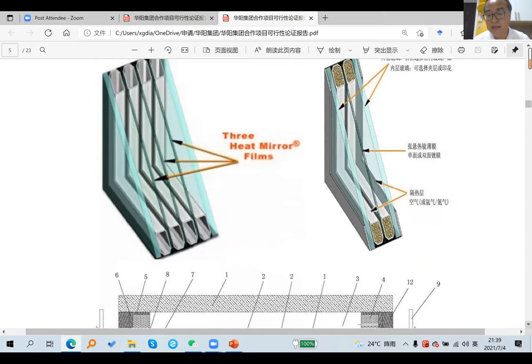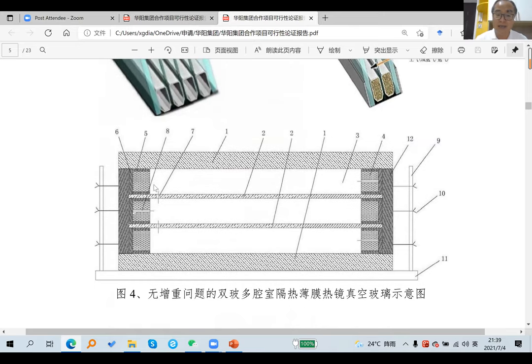So people are developing alternatives. The idea is something like triple glass layers with several chambers, but in the middle people use thin films, which are not very heavy, to separate the bigger space and make several spaces. Here is glass, film, and you can get more. On the films you can put low emissivity thin films, and all the films have a maximum thickness of about 100 micron, or even 50 micron.